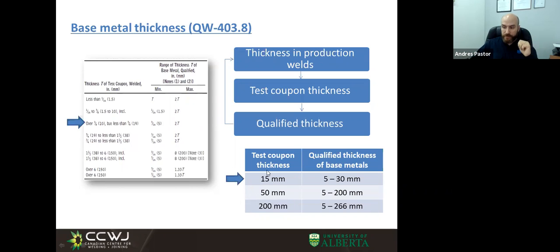So here we have an example. Let's suppose that we have a test coupon of 15 millimeters in thickness, okay? So this thickness is in this row, okay? Remember that the first column is the test coupon thickness, okay? So the minimum qualified thickness is 5 millimeters, okay? You can see it. Excuse me, I'm going to take a pencil here. 5 millimeters, and the maximum qualified thickness is 2 times capital T. In this case, capital T is 15 millimeters, okay? So the qualified range in this case is from 5 millimeters to 30 millimeters, okay? Very easy.